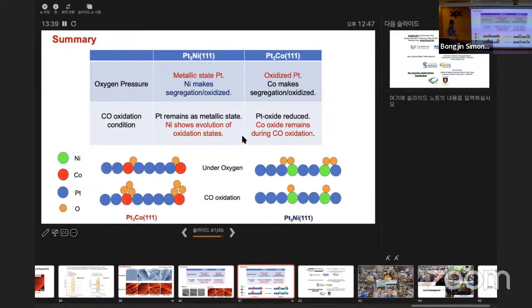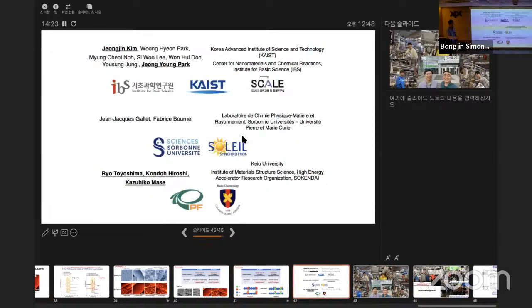And another possible scheme is that in platinum nickel, you have this sharing, with the platinum and the nickel coming up to the surface, then sharing this oxygen and forming this platinum nickel interfacial oxide. But in the case of platinum cobalt, it forms a very stable oxide on the surface that doesn't really share too much. And the platinum that shares the oxygen gets activated and then gets reduced. For platinum-3 nickel, we more or less wrap up the study, but for platinum-3 cobalt, we are still working with DFT calculations and trying to explain what we just saw.